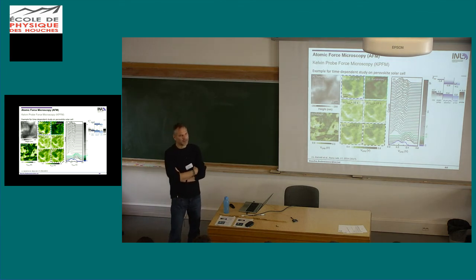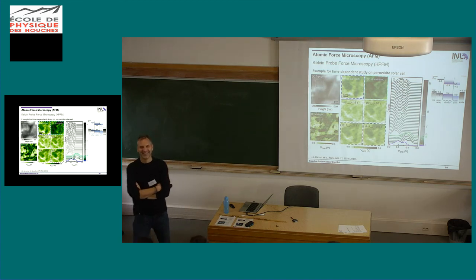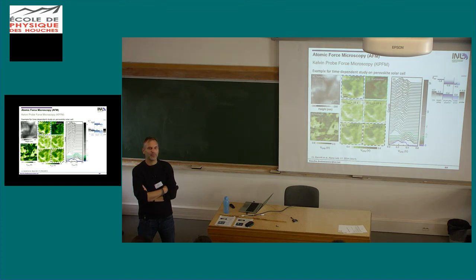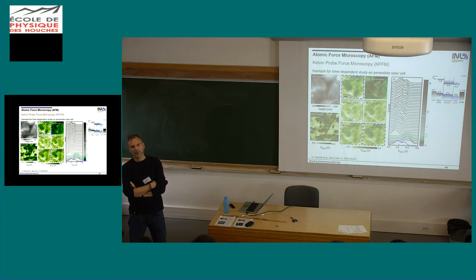We should have a question from a student, I think. Yes. I have a question on organic bulk heterojunctions. Conventionally, when they try to image the domains, they use a very thin layer and then do STM. But I don't think the same domains are captured when you make a thicker layer for a solar cell absorber. So is there any way of doing it with an AFM and a thick layer of absorber? As far as I can tell, at least for KPFM, most people use the regular thickness for imaging bulk heterojunction materials. There has been quite some work done on this. For STM, maybe it's because the materials are not as conductive, and that's why they use thinner ones. But I don't know much about these materials, so I'm afraid I cannot answer your question. But I think in KPFM it has been done on regular thicknesses.